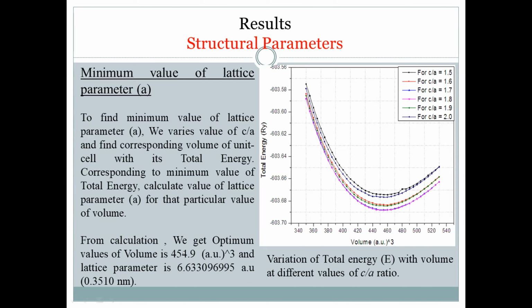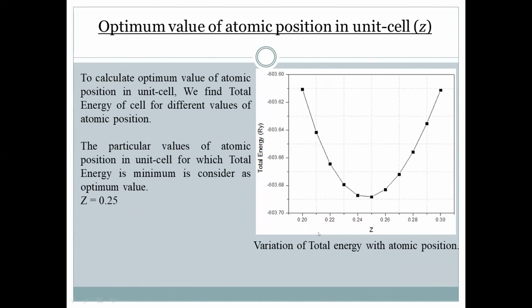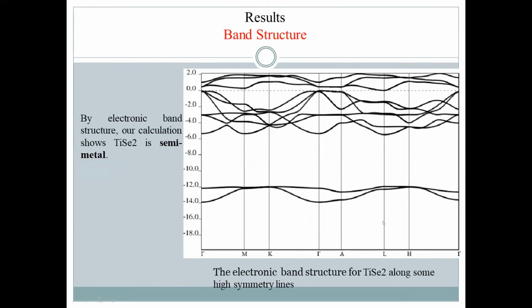We get a minimum value of 454 angstrom cube and the lattice parameter is 0.351 nanometer. After finding the minimum value of the lattice parameter, we move to find the optimum value of atomic positions in the unit cell for Ti and Se2 atoms. By Quantum ESPRESSO, we get 0.25. Here 0.25 represents the position of the Se atom on the Z axis in the Cartesian coordinate system.